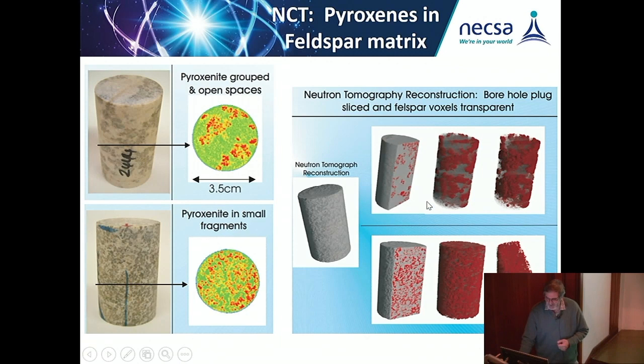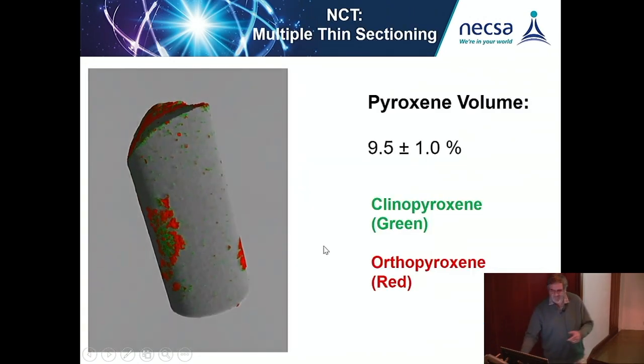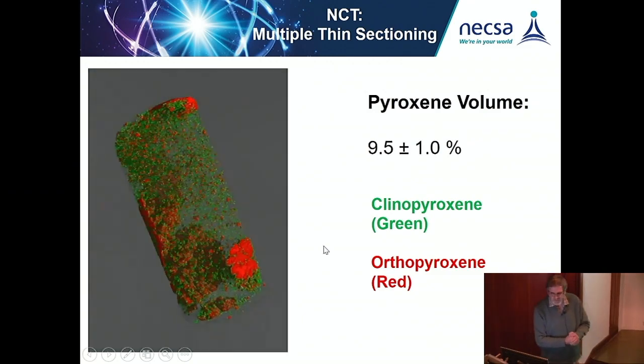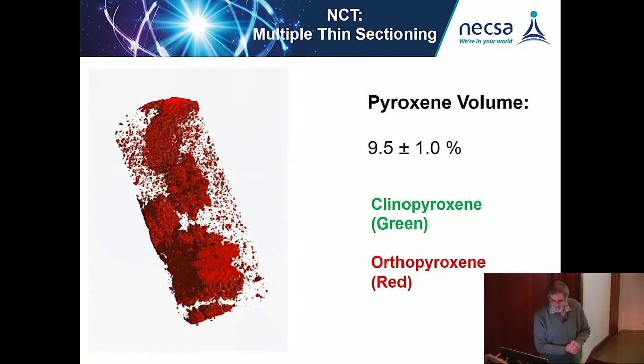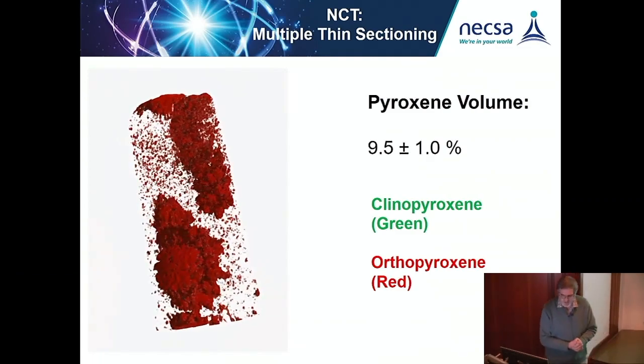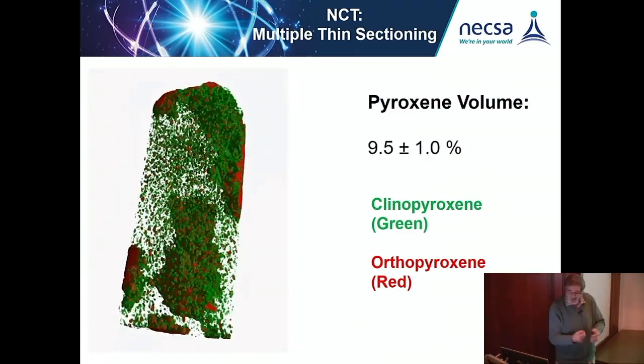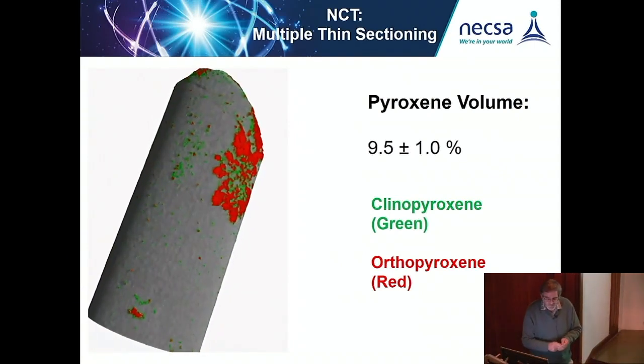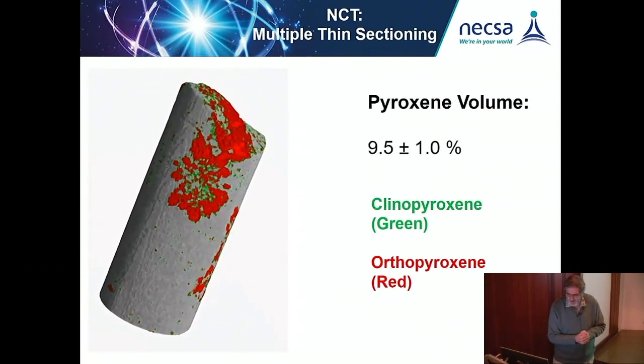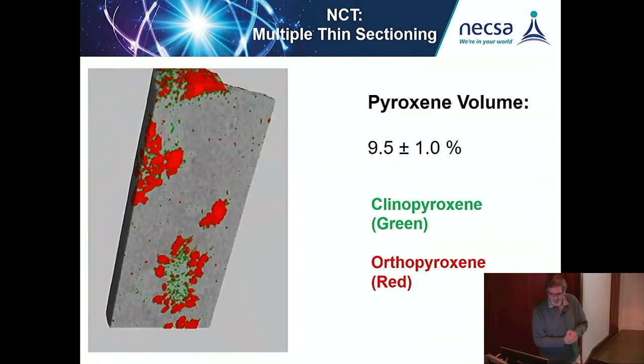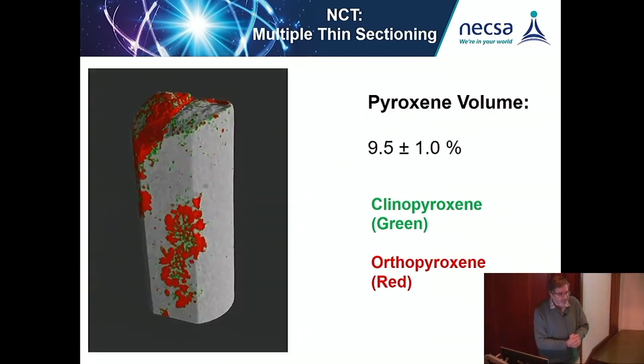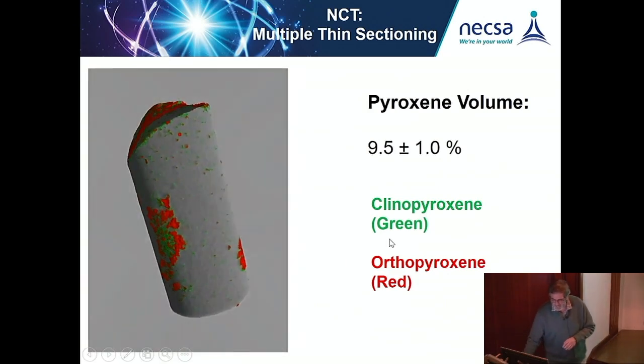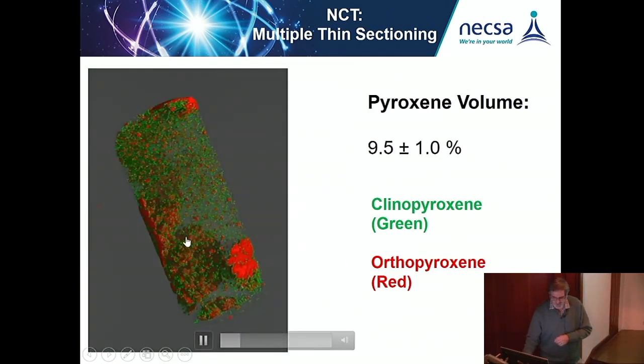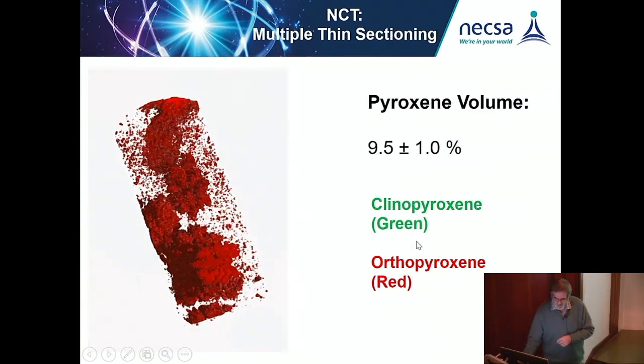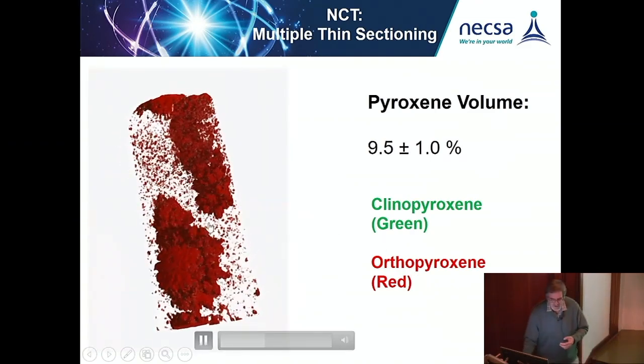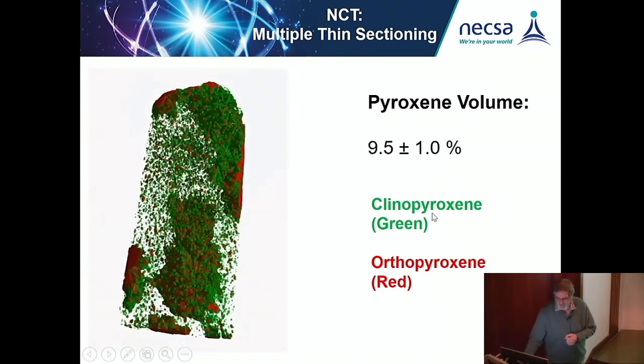Okay, so when you have this drill core, what is the process to do thin sectioning at the end of the day? Is to make a neutron scan, because the X-rays can't penetrate through the thick sample. Then neutrons can discriminate between the clinopyroxenes and the orthopyroxenes, because I think the clinopyroxene has only a calcium atom added to its matrix, and therefore, although these two minerals have the same density, the neutrons can separate and distinguish between those two minerals.